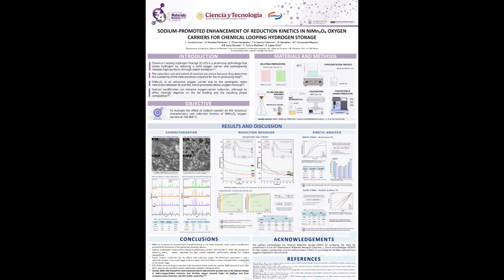Chemical looping hydrogen storage, or CLHS, is based on cyclic redox reactions involving a solid oxygen carrier. During reduction, the oxygen carrier reacts with hydrogen and forms a reduced solid. In a complete chemical looping hydrogen storage cycle, this reduced phase is subsequently oxidized with steam to produce hydrogen. Because of this, the reduction behavior of the oxygen carrier represents an important part of the overall process. Both the reduction rate and the achievable conversion determine the availability of the reduced phase for the following step.